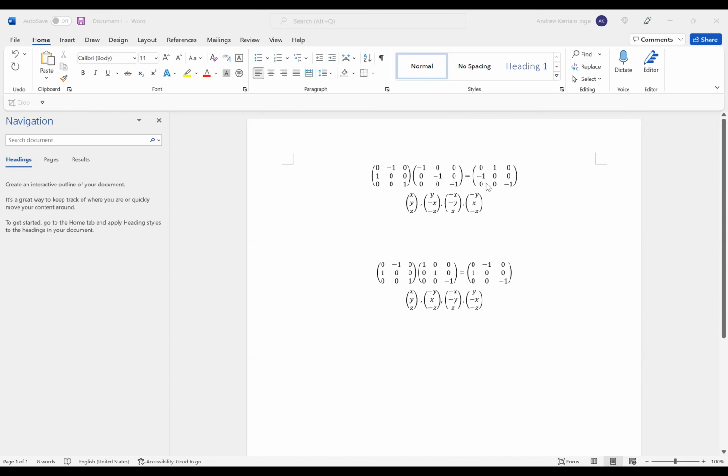Record this too. Okay, so I hope this is right. I'd be embarrassed if it's not. So this is the fourfold rotation around Z; I just took Z as the axis that I was going to rotate around. So this is fourfold rotation around Z, and then I invert it. This is your typical rotoinversion with the rotation down Z, and this is the matrix that I get out in the end: 0, 1, 0, minus 1, 0, 0, and 0, 0, minus 1.